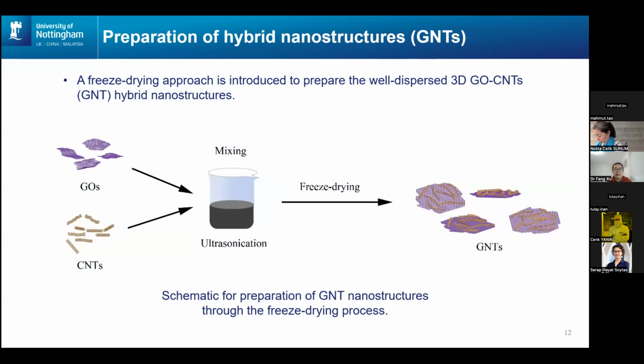We all know that if we mix something in solvents, when we dry them, they tend to agglomerate again, no matter how well they have been dispersed in the first instance. So we propose using a method called the freeze drying approach.